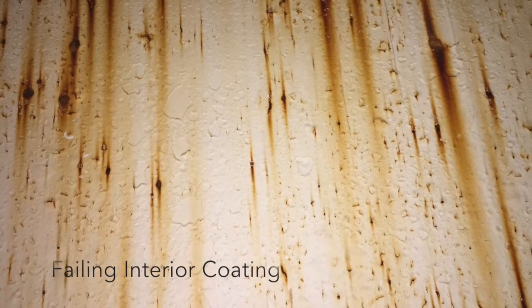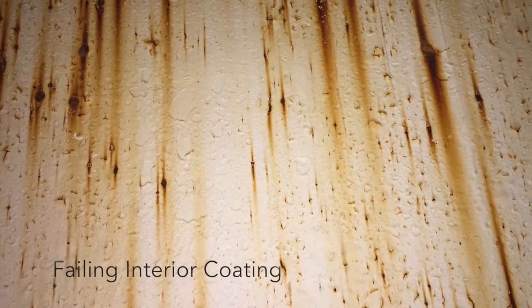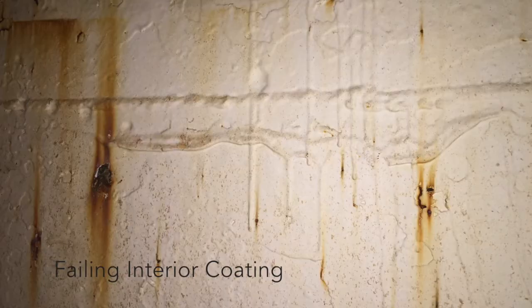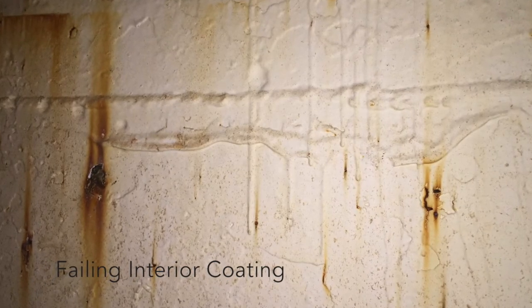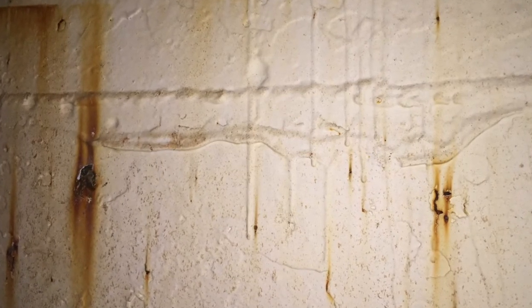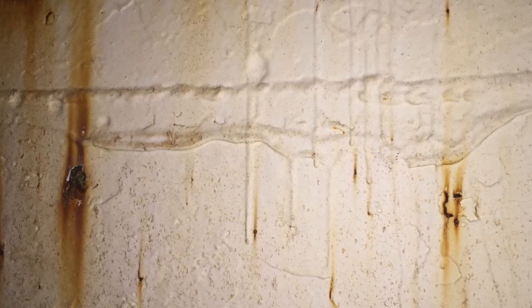The interior coating was applied very poorly at an inconsistent thickness over little to no surface preparation right over the previous coating as well. This resulted in coating runs, blistering, rust, staining, chipping, and delaminations. There were many large pits on the interior surface and holes in the tank wall.